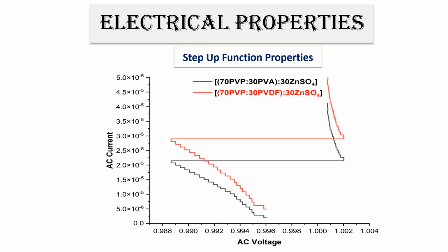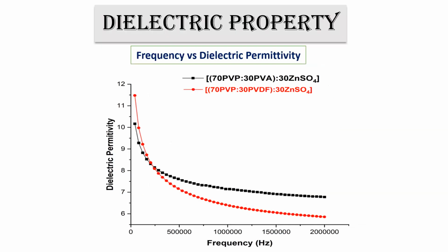The step-up function shows some transitions when we use an AC voltage around 0.98 and 0.998 volts. Both samples show the transition shifting in different manners. The steps are quite similar, like stairs, so due to the stairs or steps, it is called the step-up function. It's really very useful for optoelectronic devices. So it's an interesting feature, and interesting data for me to show all of you.